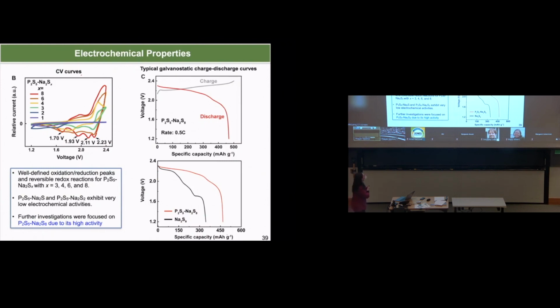I want to highlight something if you bring your attention to this figure here. This is a conventional liquid cathode material, the black curve, compared to this red curve, the complex material we developed. We find that the electrochemical potential is much higher compared to the conventional case. This is a good thing because the higher voltage you can get for a battery system, the higher energy density you can deliver. So for this new complex material, we can achieve a higher capacity, and we can also achieve a higher voltage compared to the conventional case.